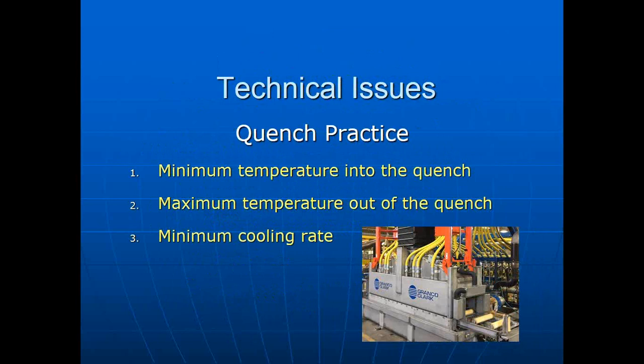Quench practice we're going to focus on extensively, but we will come back to these three primary factors. There's a minimum temperature into the quench. It has to come in hot. There's a maximum temperature out of the quench. It has to come out colder than a temperature. And we need a specified cooling rate between the two. And again, we'll come back to this.